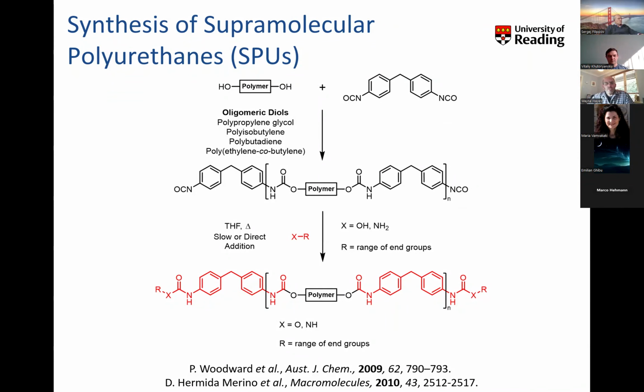Then by judicious use of an appropriate nucleophile, you can end cap that diisocyanate precursor, which will be reasonably chain extended, but we can control that by the monomer feed to afford the desired supramolecular polymers shown at the bottom in red. And we've primarily played around with either alcohol or amine nucleophiles to generate urethane or urea end groups.